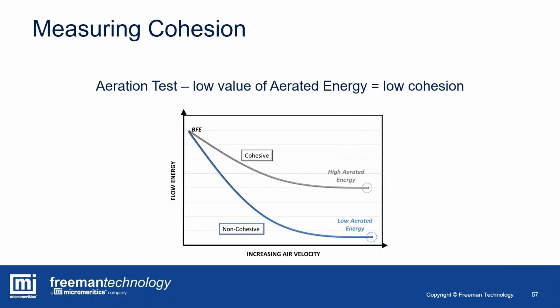So we measure cohesion, in my opinion, the most direct way through the aeration test. So what you have here is the flow energy of the sample, and we measure it as you go from 0 gas velocity to an increasing level of aeration. And so for non-cohesive powders, where the cohesive or the tensile forces that hold particles together are weak, the powder is able to fluidize or fully aerate as that gas permeates through the powder bed and it pushes the particles apart. They're not stuck together through high electrostatics or high cohesive interparticulate forces. And as a consequence of that full aeration or fluidization process, the resistance to flow reduces to an asymptotic and very low level.